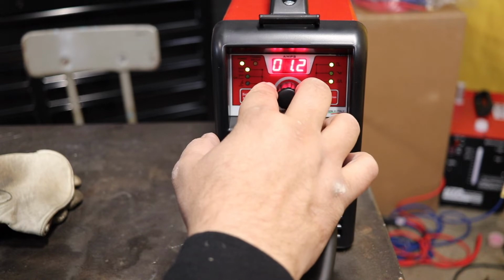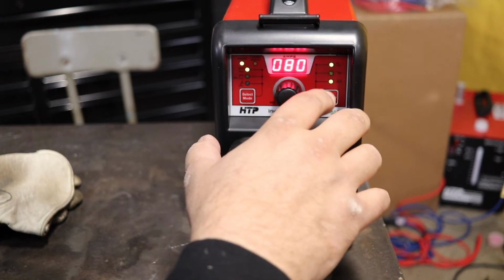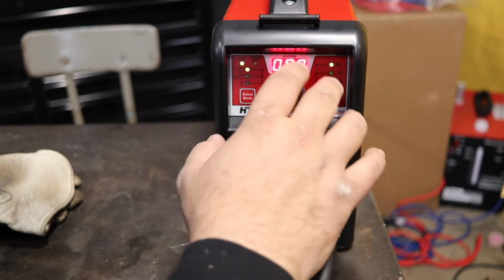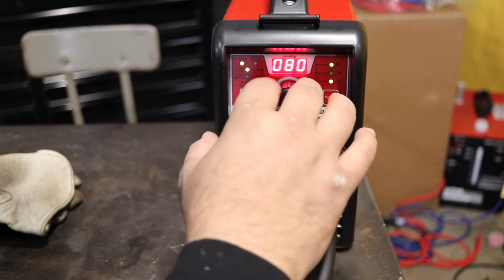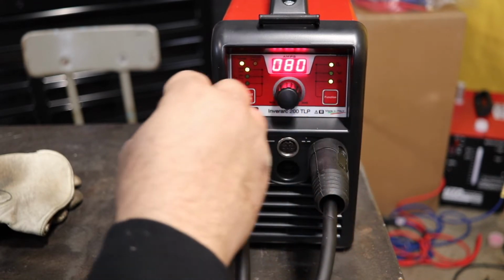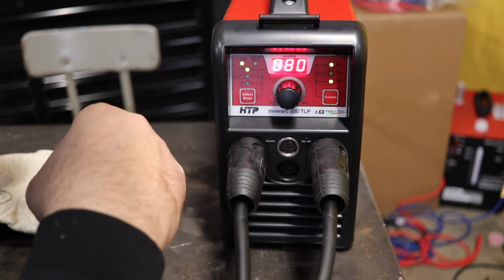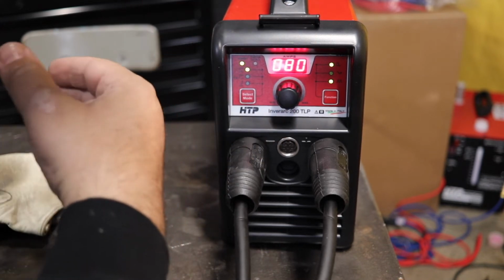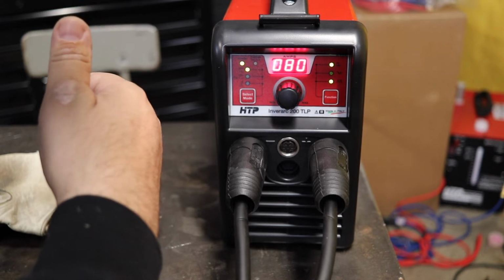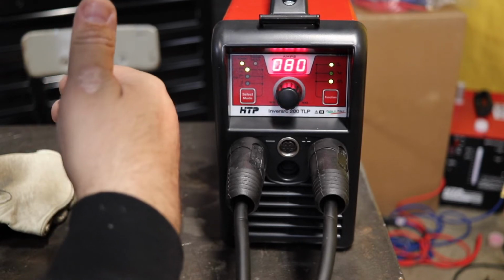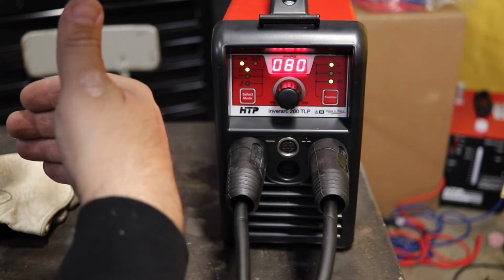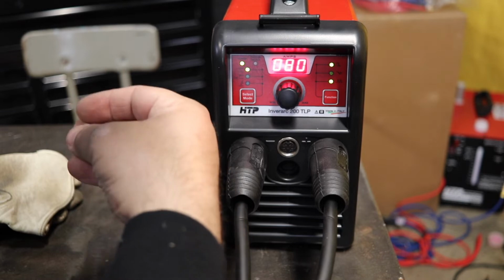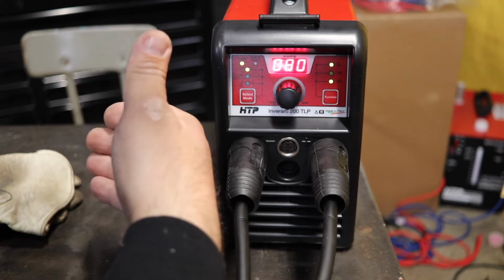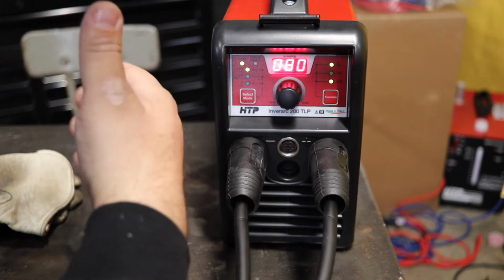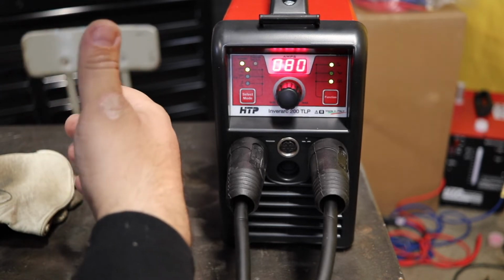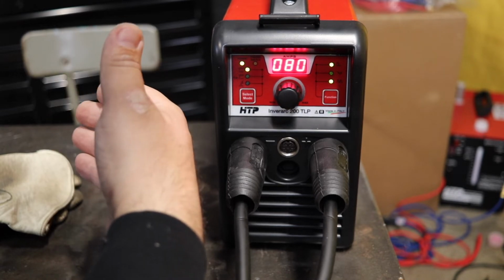I find I like pulse frequencies around 1.2 pulses per second for steel. On aluminum, I like 2.2. Very rarely I use a higher pulse. Although theoretically we could make the machine with a very high pulse frequency, once you hit 6 or 7 pulses per second, there really is not enough cooldown time between peak pulses, so the desired effect you get from the pulse is vanishing the higher your pulse frequency goes. And I found that frequencies under 0.8 pulses per second are very hard to weld because you have a very long on time as well.